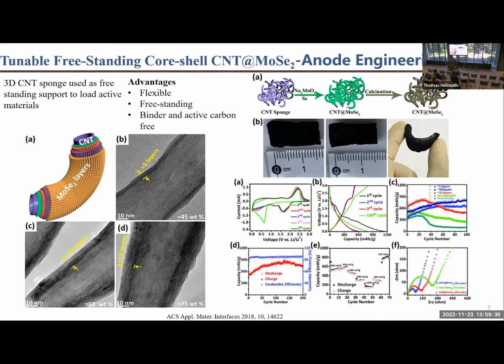Then in another experiment, we wanted to see how much active material we can load. Generally, we see that if we can load more active material, we can get more performance. But we wanted to see where is the limit, how much active material is the best, whether it can perform if we go 5, 10, 15, 20, whether it always keeps on increasing or not. So we chose the layered material like molybdenum selenide and loaded it onto carbon nanotubes. So we controlled the loading mass to 5 layers of molybdenum selenide, 10 layers, 15 layers.